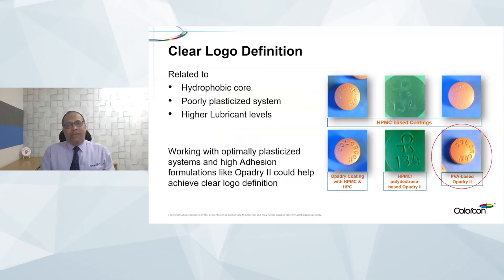The last slide: ultimately, the tablet has a logo to identify the strength or the manufacturer's name. I think it is important to ultimately get this right as well. There are cases where the API is too hydrophobic, or the coating system does not have sufficient plasticization, or in a few cases where we use higher than required levels of lubricants, which creates hydrophobicity on the surface, and that's where there could be a possibility of getting the logo defects like we see on top. Examples are the traditional coatings which are based on HPMC compositions. Of course, it doesn't happen on all products, but those sensitive core tablets or substrates are where you could see it. Working with more optimally plasticized systems and good adhesion systems would help achieve a very good, clear definition of the logo, as you can see in the examples below.